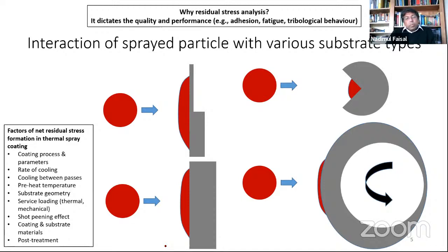Right, so to start with, we know that in thermal spray, you've got particles at very high velocity and temperature, which interact with the surface. Now, the surface can be of various shape and size. Here, you can see on the screen a thick sample or a thick combined with a thin sample. You can be spraying in corners or bends, or you can be spraying on rollers. In all these cases, the geometry, the shape of the substrate, will have an impact on the strain which will build up during thermal spray.